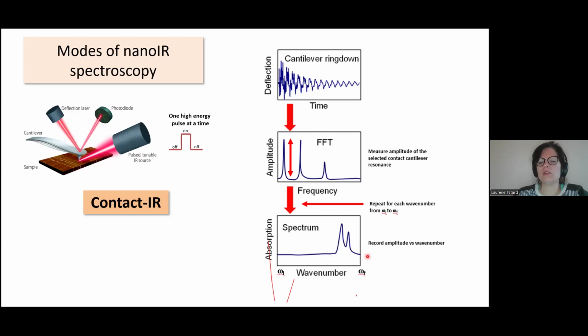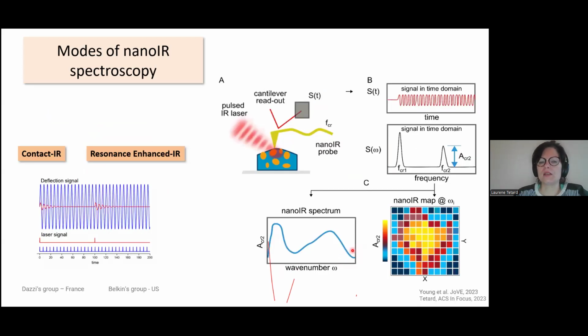So that's been confirmed that the infrared spectra you collect that way, they match, they agree with FTIR spectra. The bands are at the right place, at the right position. So you're actually measuring the vibration of the bonds that correspond to what is in the sample. And after that, the technologies evolved to make the measurement faster, more sensitive, to allow chemical mapping by reducing the time it takes to acquire spectra and things like that.